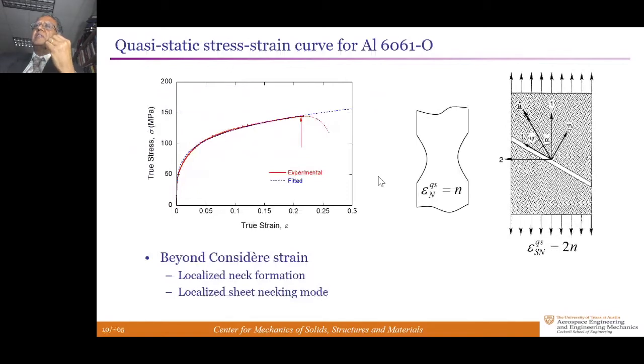So the question that people raise is, what happens if the strain rates are large? Strain rates not quasi-static, on the order of 10⁻³ per second or so, but 6 to 8 orders of magnitude larger, 10³ to 10⁵ per second. Basically, two things could happen: a necking of this kind here, or a sheet mode necking of this kind, where it thins in the third dimension but has a band at different orientations depending on the plane stress, plane strain constraints of the body.